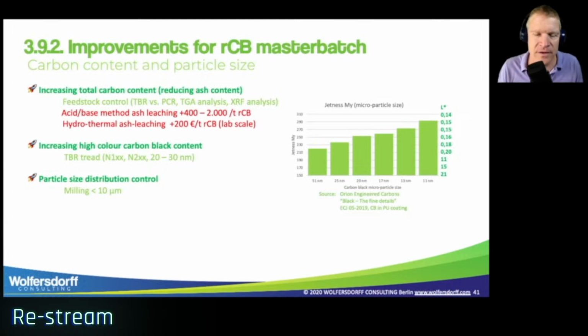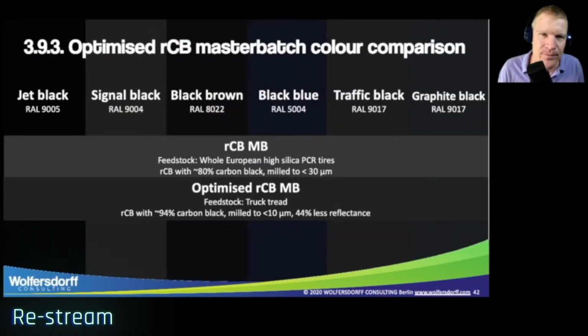We have to mill very finely. Now, milling is not really going on the blackness. This is really the microparticle size, but the milling is more the recovered carbon black aggregate size. But the aggregate size also plays on how we can disperse and how we can distribute the recovered carbon black in the master batch and in the final application. Here, I would recommend a milling below 10 microns.